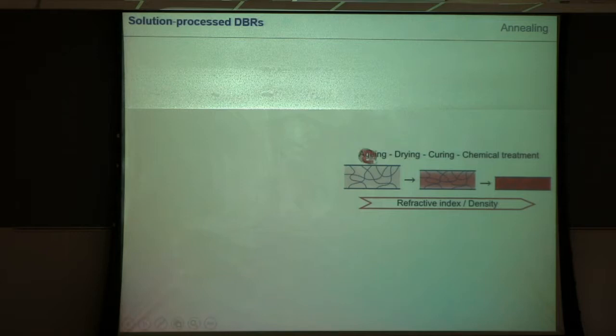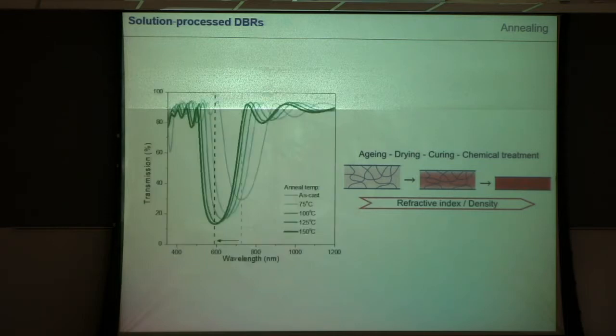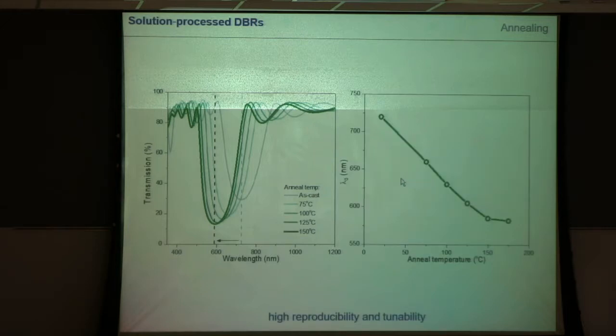What we use a lot is the post-annealing. As I showed, with increasing the temperature, we can change the refractive index of the material. And this simply has to do with the densification of the material. So in the same volume, you have more titanium. This is very reproducible, so we can make master curves of how the stop band of a made mirror shifts. So we can make a mirror, and depending on application, we anneal it at different temperatures. We get different refractive indices and thicknesses. So the optical thickness, refractive index times thickness, changes. We know why. And therefore, we can change the mirror. So this is highly reproducible.